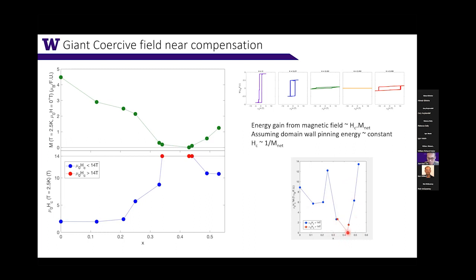This red data point is not really reliable, since this data point is really beyond our 14 Tesla magnet to extract the coercive field. Okay, so this is the coercive field. Let's look at the temperature dependence of the magnetic behavior of this system.